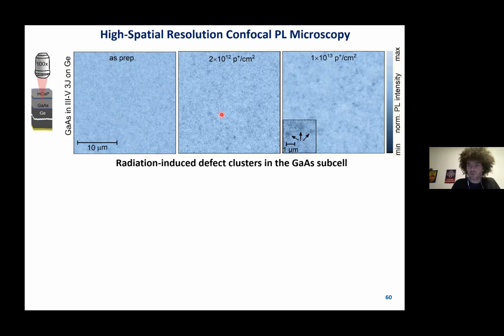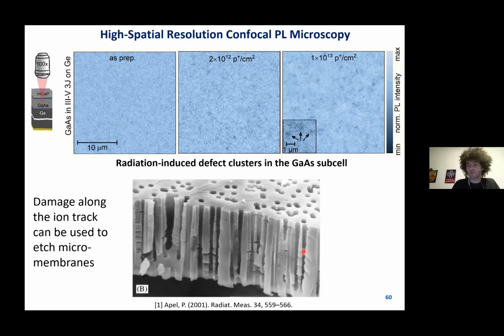But then upon proton irradiation, we start to see these dark spots here, which appear to be defect clusters. And they're very similar to what is known for the damage from proton irradiation, for example, in polymers or plastic. So there you can actually etch along the damage of this ion track. So if you imagine one proton flying through here and damaging the material along the track, and then you can etch this damage to produce these micromembranes. And what we see here in the PL seems to be quite similar. So we see defect clusters probably around the ion track of the protons.